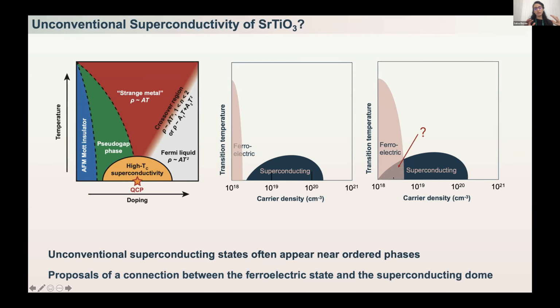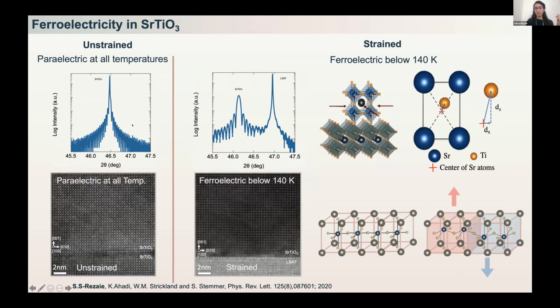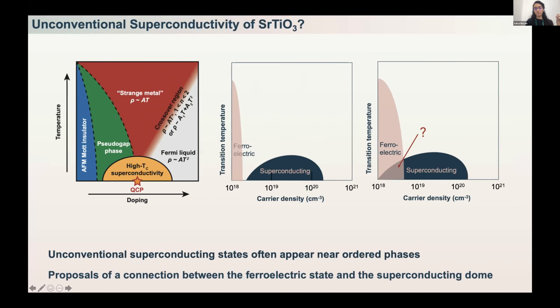But we wanted to know whether there is any correlation between the superconducting state and the ferroelectric state in this material, and whether these two orders are competing or cooperating with each other to give the superconductivity that we want. This brings up another question: whether the nature of superconductivity is unconventional or conventional, because oftentimes unconventional superconductivity happens next to another order parameter, for example in the case of cuprates, where superconductivity happens next to antiferromagnetic fluctuations.